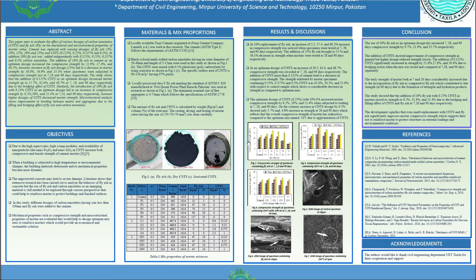The results show that when cement is replaced with fly ash at dosages from 0 to 25 percent, the optimum dosage was 10 percent, which increased compressive strength up to 55 percent at 28 days. Looking at figure three, the addition of different dosages of CNTs also enhanced compressive strength.